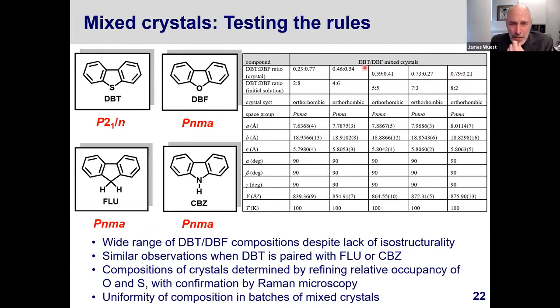What is remarkable about this is that this range of compositions can be attained despite the fact that the two compounds do not crystallize isostructurally. The other thing is that over this entire range, the crystals are always the Pnma structure of dibenzofuran. This is unexpected because it means that even if you replace the smaller furan by the larger thiophene, 80% in fact of the thiophene, you still get crystals forming in the furan structure.